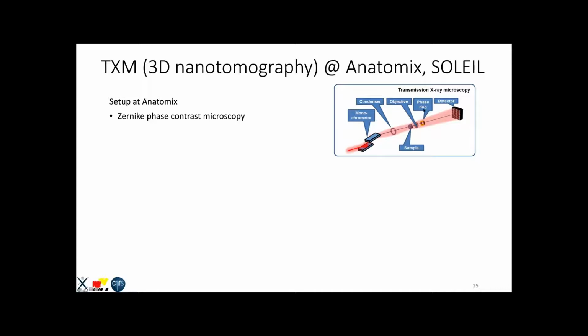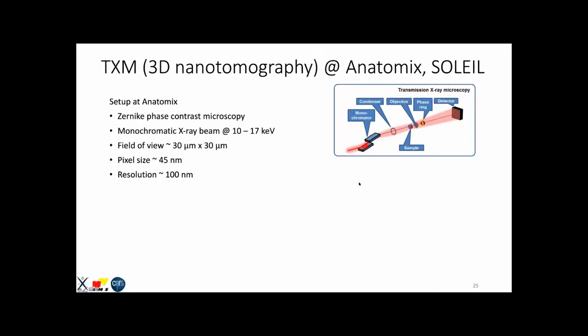Then this phase ring is trying to increase the phase shifts such that there is destructive interference between parts of the signal that is coming out. And once that has happened, there is a detector that detects these phase shifts and reproduces them as brightness changes in the images.